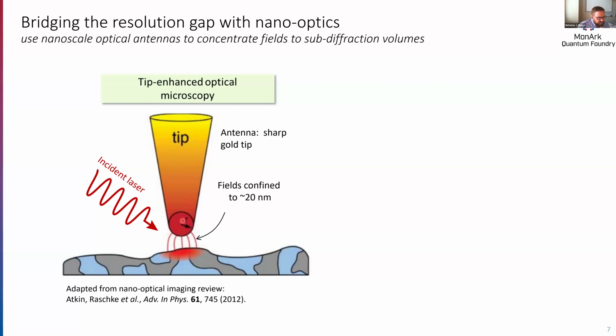This incident laser causes the conduction electrons in the tip to oscillate at the same frequency as the incident laser. And the net result is you get a concentration of localized oscillating electric fields right at the apex of the tip. These fields are confined to length scales determined by the radius of curvature of the tip, which can get down to about 20 nanometers in space. And so you can use these oscillating electric fields at the tip as a local light source to perform optical microscopy and spectroscopy.